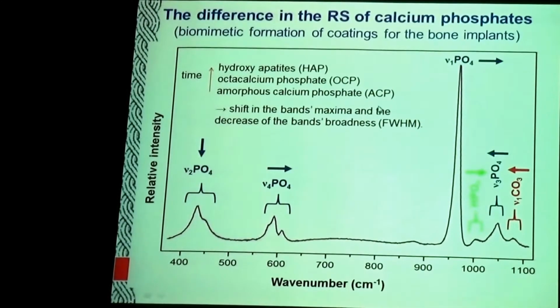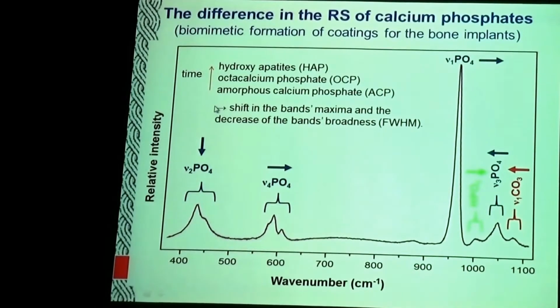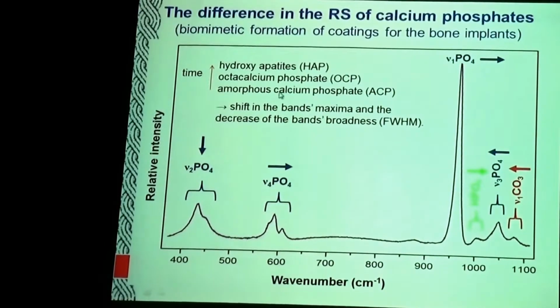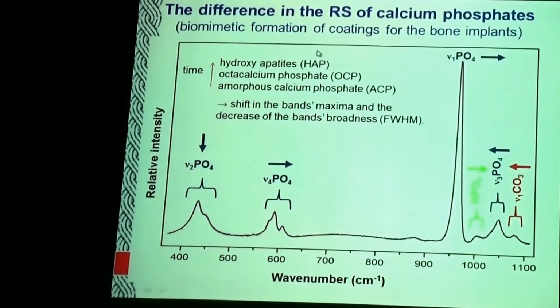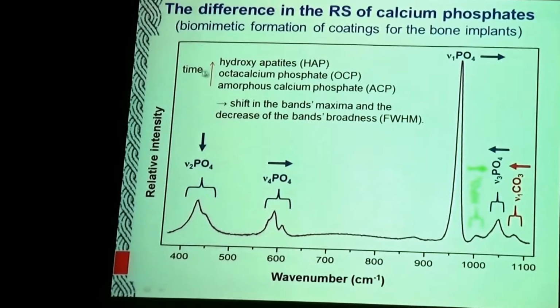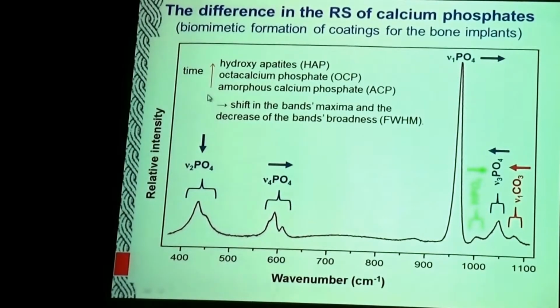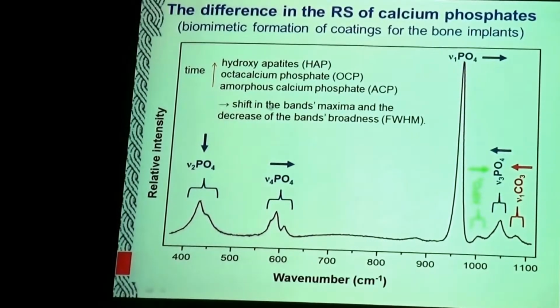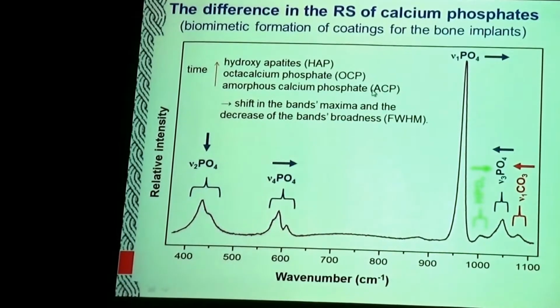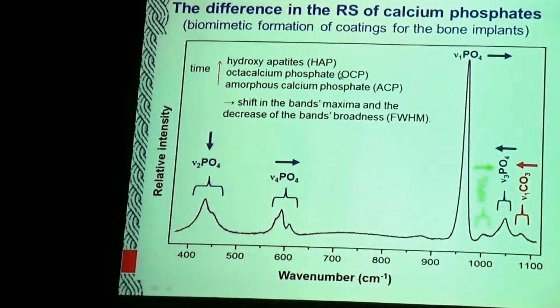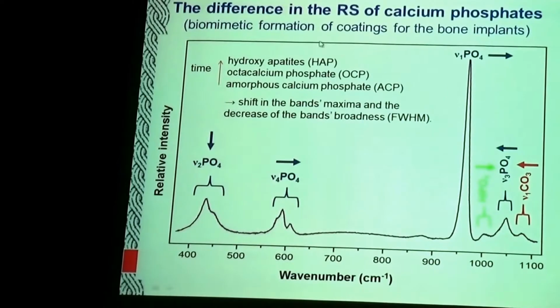So when we use the calcium phosphate system, and when we would like to achieve different phases of calcium phosphate in solution, we need different times to prepare amorphous calcium phosphate, octacalcium phosphate, and hydroxyapatite.